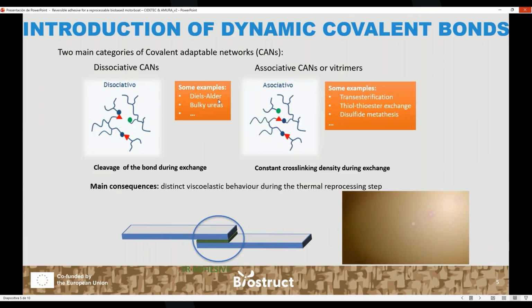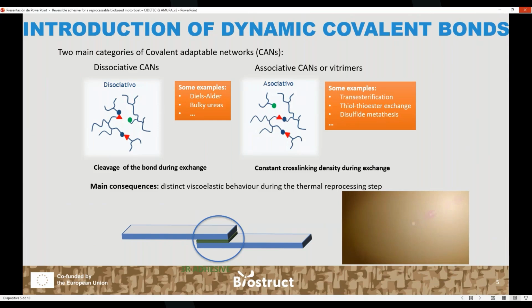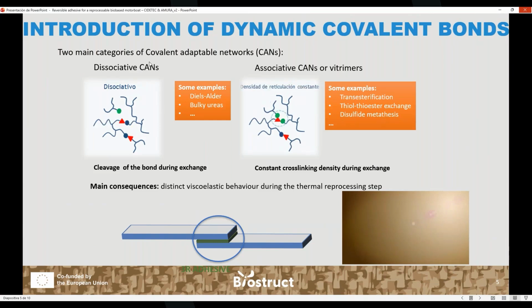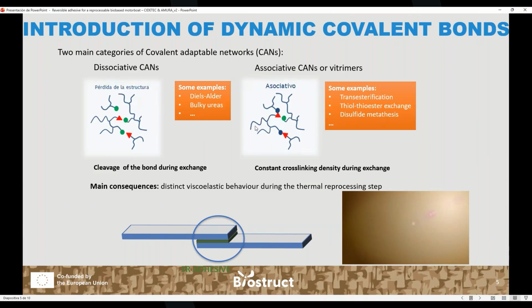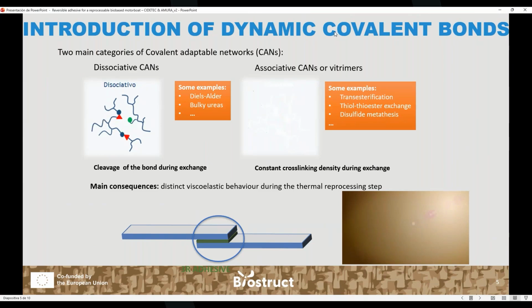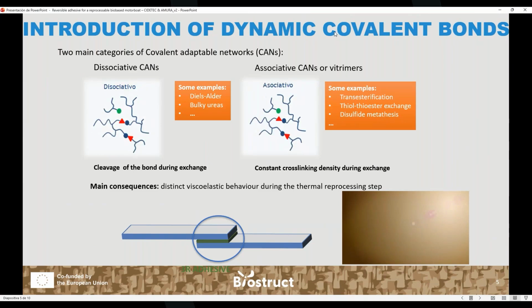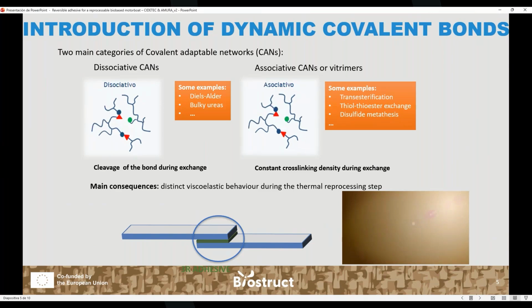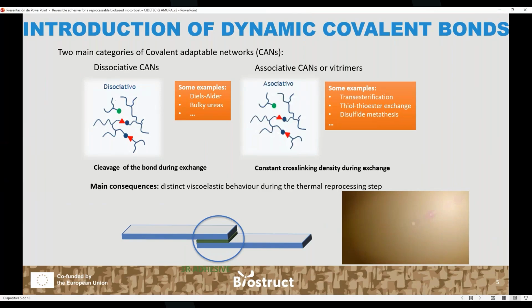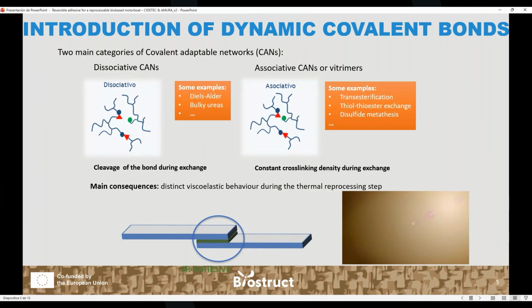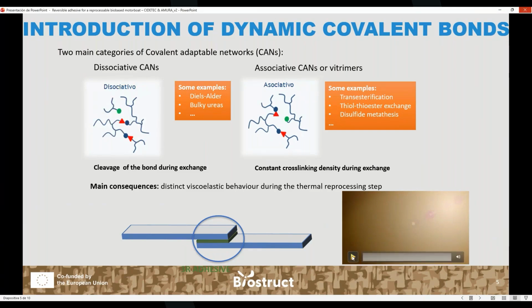In dissociative networks, we obtain a cleavage of the bond during the exchange, and in associative networks, we obtain a softening of the material while constant cross-linking density is maintained. The main difference between these two covalent adaptable networks is the distinct viscoelastic behavior during the thermal reprocessing steps. And here in this project, we will introduce aromatic disulfide bonds, which are associative, to obtain an associative-like network. Here in the following video,